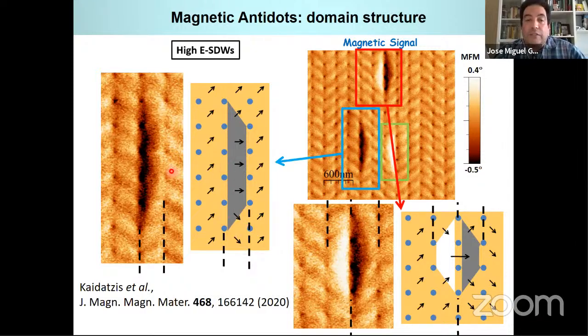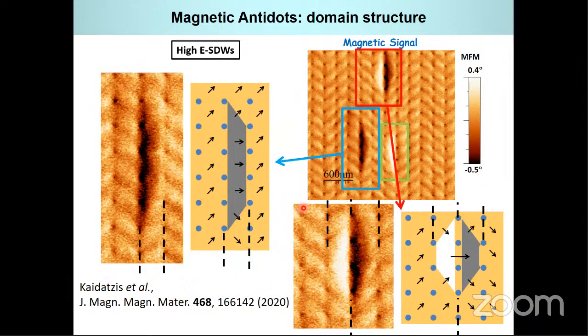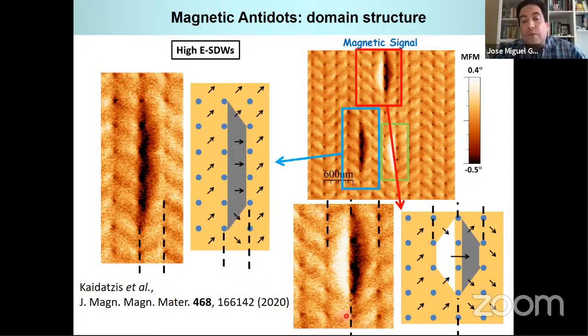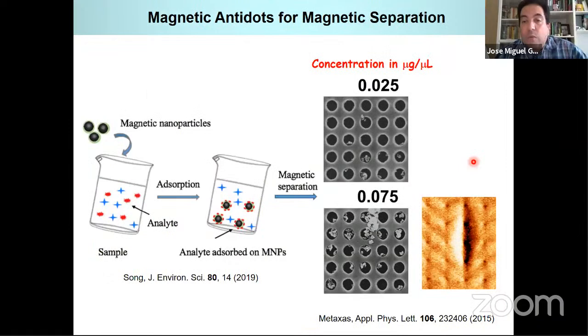And this structure is developed. This is called a high energy superdomain wall. And when we have 1, 2, 3, 4 low energy domain walls that end in a region, we have dipolar contrast with this spin structure. So this explains why when we use the magnetic antidots for magnetic separation, the magnetic nanoparticles accumulate in some regions. Those are the regions that exhibit these high energy superdomain walls.